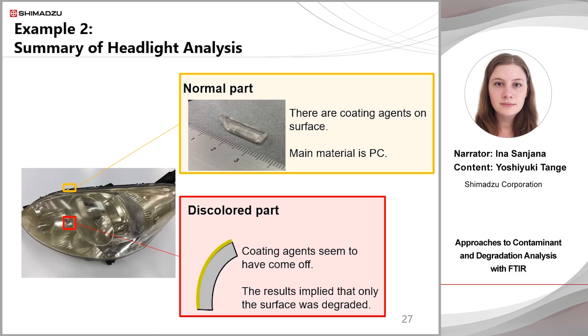This is a summary of the analysis results for the vehicle headlight. From the analysis of the normal part, the base material was confirmed to be polycarbonate, and a coating agent containing PMMA was detected on the surface. On the discoloured part, no peak from this coating agent was observed on the surface. The degree of deterioration was about the same as that for plastic exposed to ultraviolet light for 550 hours in the ultra-accelerated weathering tester, and this degradation was limited to the surface.